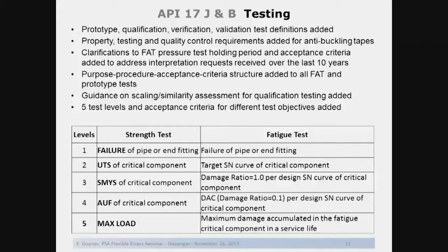Similarly, for fatigue testing, we have test failure, testing to a target testing curve, which is typically defined as mean plus 3 standard deviations, testing to a damage ratio of 1.0 for the critical fatigue component, testing to the design acceptance criteria, which includes the safety factor of 10, or to the maximum damage accumulated in a fatigue lifetime.